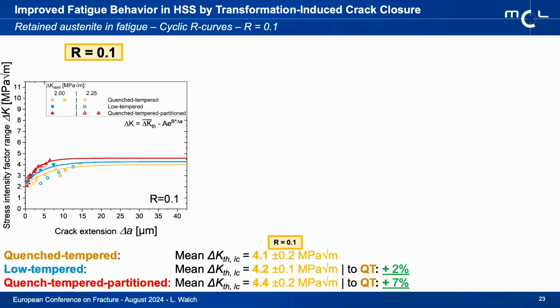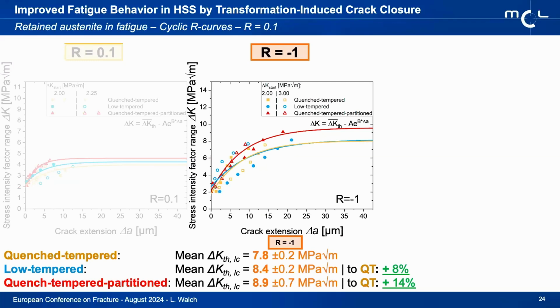For the cyclic R curves, you can already see that, especially for the quench tempered and partition material state, the R curve itself seems to have a steeper slope towards the final plateau, and also a higher plateau that is also indicative of the long crack threshold. Whereas the other 2 material states aren't quite distinguishable, especially not with the scatter that we just have to live with.